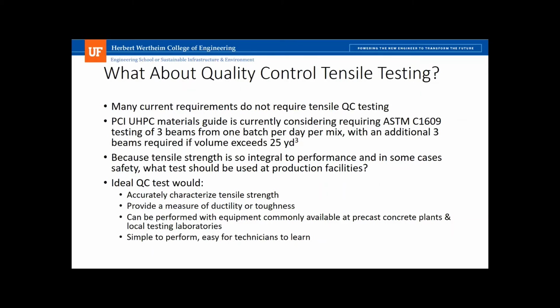So many times no tensile testing is done at all. They just rely on the compressive strength testing and rely on the tests that were done during qualification. We assume that it's going to be okay. We assume that the right amount of fibers have been put in, which is a big assumption since at many plants, they're added manually. It's very easy to miss a sack of fibers.